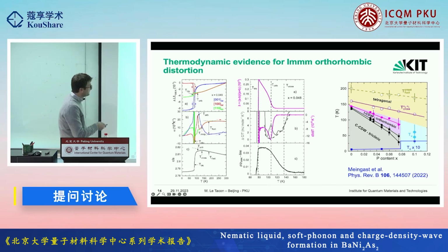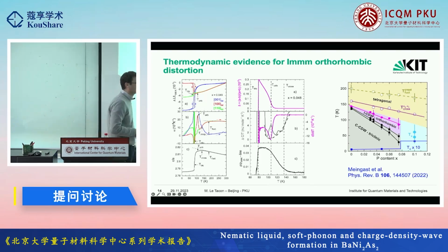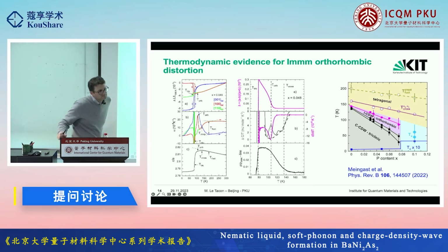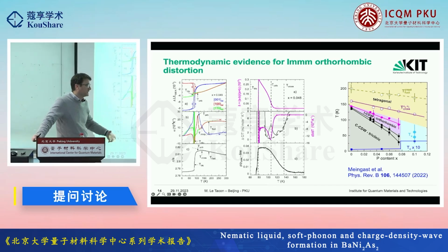I mean, and this is a very, very tough judge of whether the system is tetragonal or not. I mean, thermal expansion. If you have this high resolution, right? So, when thermal expansion tells you the system is tetragonal, it's really tetragonal. I guess you need to measure the in-plane properties, just rotating with respect to one axis, the A or B axis, to see some kind of twofold symmetry. Yeah, I think in this system, the resistivity and magnetic susceptibility show only weak signatures of the actual transition. So any regime above this transition is very hard to detect.